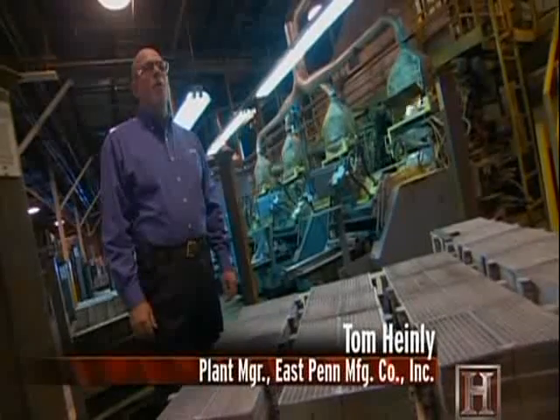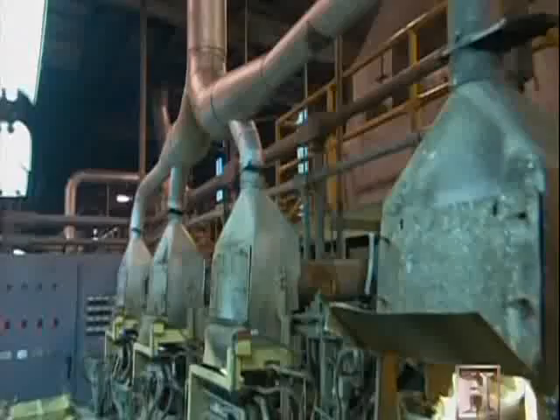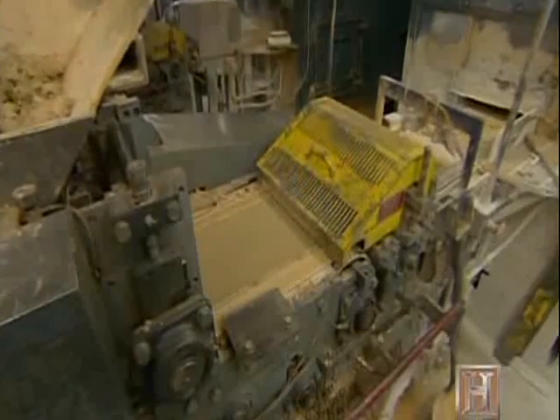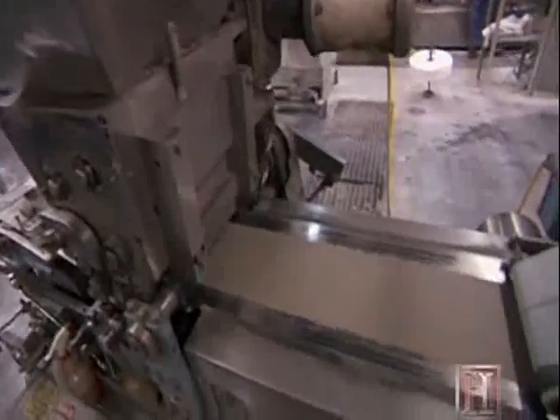First step in making an automotive battery is to make a grid, the framework for the plates. So what we're doing is we're taking hard lead, putting it into a 16,000-pound pot. We're melting that lead, pouring it into a book mold, and we're casting the grid work for the battery. The grids then undergo a process that coats them with a lead oxide paste, aptly nicknamed mud. These are now the positive plates that will make up the cathode. On another assembly line, grids spool off a reel and are coated with a different mud concoction that creates the negative plates for the anode.